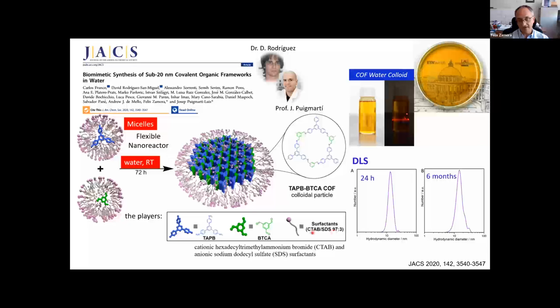When we form these nanoreactors and then mix the two initial building blocks, after several hours we observe that we form, for instance, this COF with this structure. And if you characterize the COF using DLS, you can observe a hydrodynamic diameter of below 20 nanometers. So this is the final result of this reaction, which consists of a water colloid, and it's pretty stable. As you can see here, 6 months later, we have about the same.